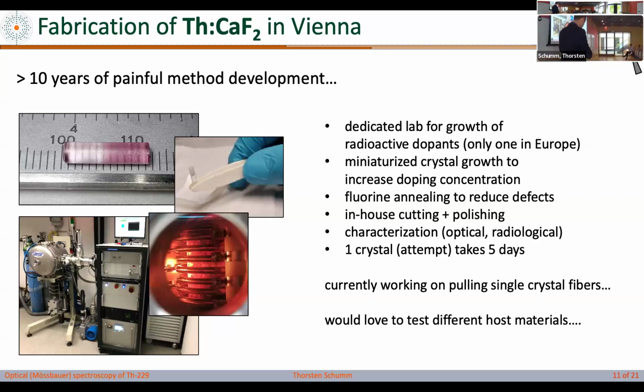The way we do it is we buy a commercial calcium fluoride, the best you can get on the market. Then we mill it down to little sticks which are 3 millimeters in diameter and about 1 centimeter long. And then we send them to a company that I will disclose over coffee that is actually able to drill a 2 millimeter hole into a 3 millimeter single crystal.